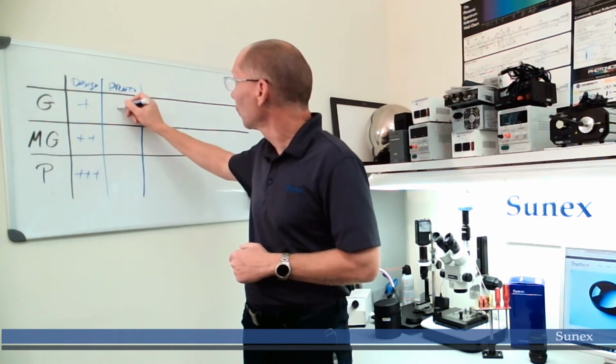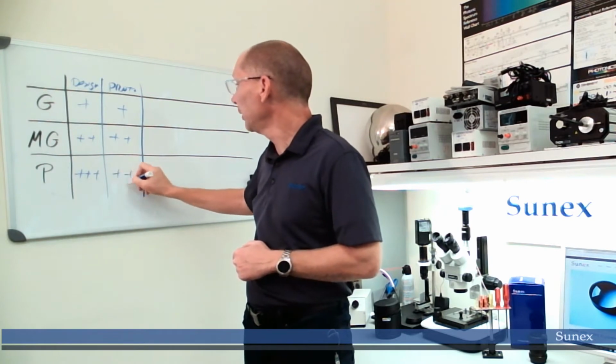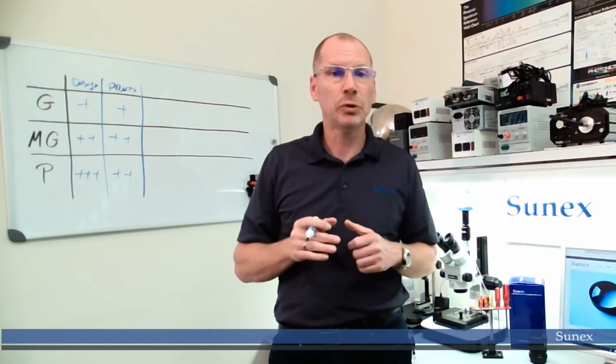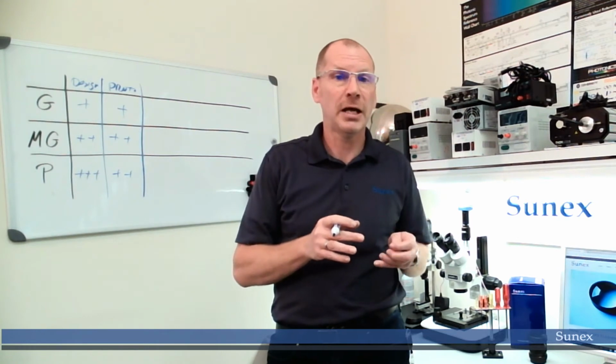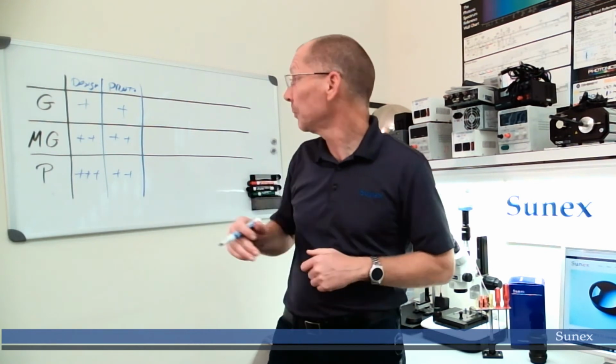Plastic molding. So we also have diamond turning in-house, which again can be applied to all three. It depends a little bit on the shape and material choices. For instance, with plastic prototyping, you want to make sure that you pick a material that can be diamond turned as well as later injection molded, so you avoid a material change throughout the design cycle of the program.